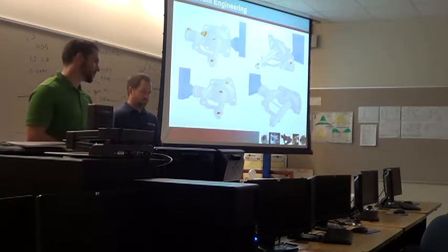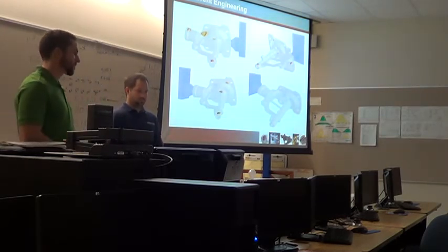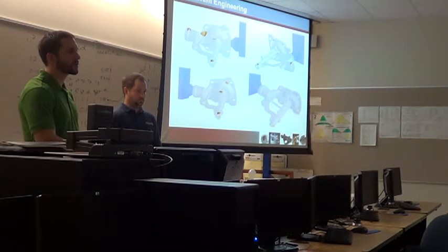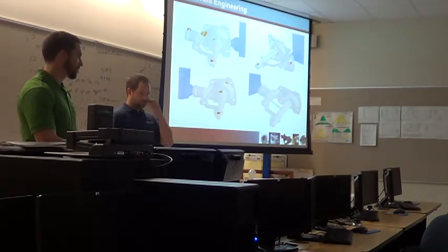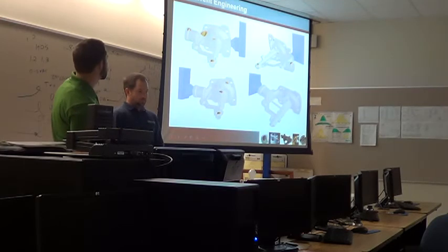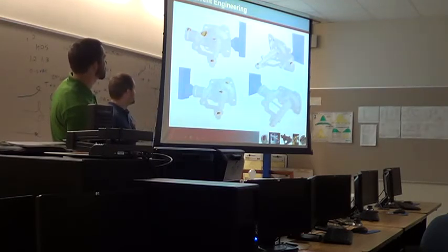Here's a few examples. This is one part. It's a nail gun nose that gets bolted onto a nail gun. We tried gating this in several different locations. So you can see top left corner, these yellow spots are instances of shrink per the simulation. That was gating off the flange face. So we relocated to a little thicker mass right off the flange face. Still had instances of shrink at the extremities there.